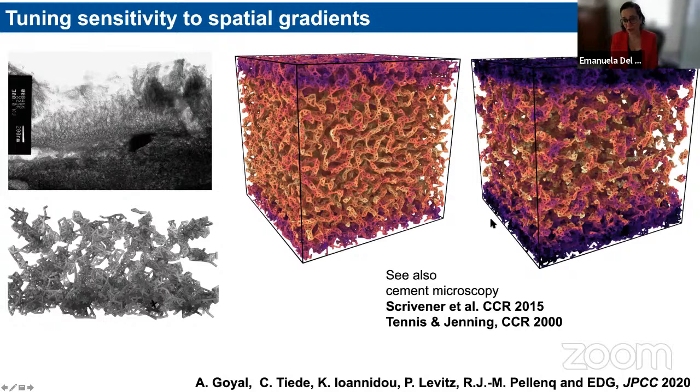And so you see that the physical picture that I was describing is actually confirmed, because the early stage interactions that lead to this more branched network with more regular pore size turned out to be also more resilient to local and chemical heterogeneities that can occur during cement hydration, whereas the later stage interactions are more sensitive to that, but they come into play at later times when the material has already gained some mechanical stability. This is very interesting for understanding how the formation of this solid material is so messy but can still be relatively robust, and it works all the time on the construction site.